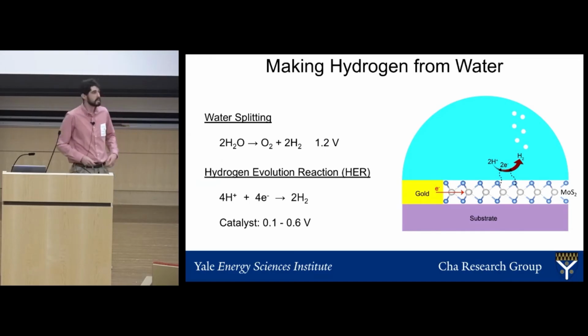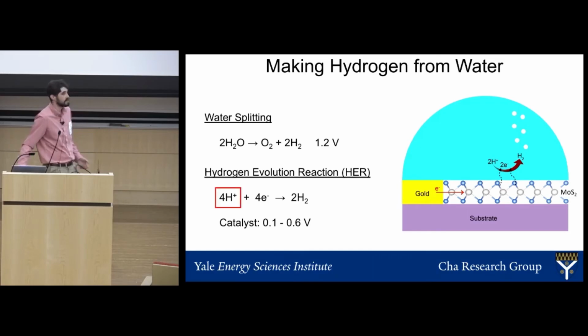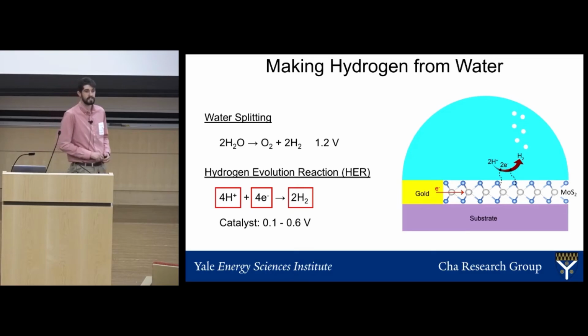So as Matt was talking about, hydrogen is a really attractive renewable fuel. And as he mentioned, we can make it by splitting water. We can zap water with about 1.2 volts of electricity, and we get oxygen and hydrogen gas. And as he mentioned, there's 2 parts to this reaction. There's an oxygen evolution reaction and a hydrogen evolution reaction. And we're interested in the hydrogen evolution reaction. So this reaction takes 4 protons and reacts them with 4 electrons, and we get 2 molecules of hydrogen gas.